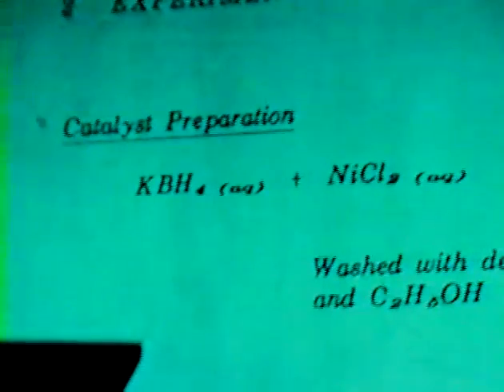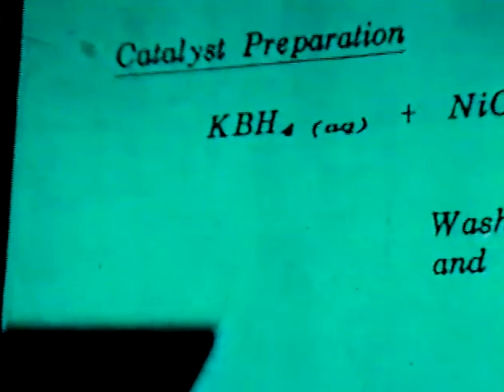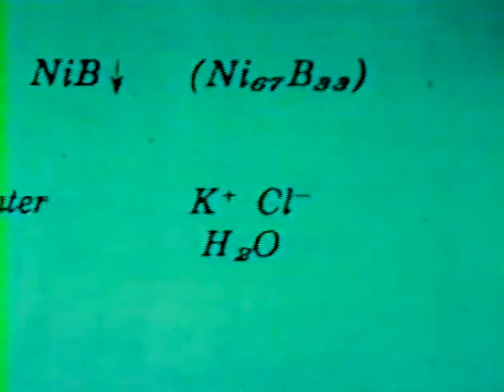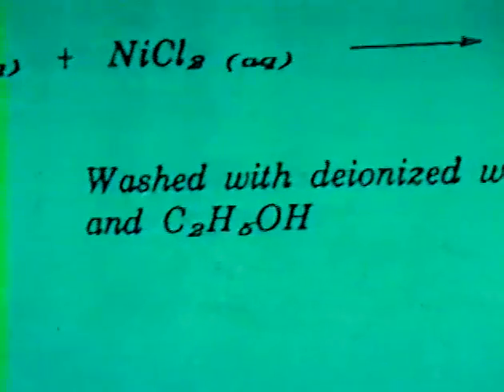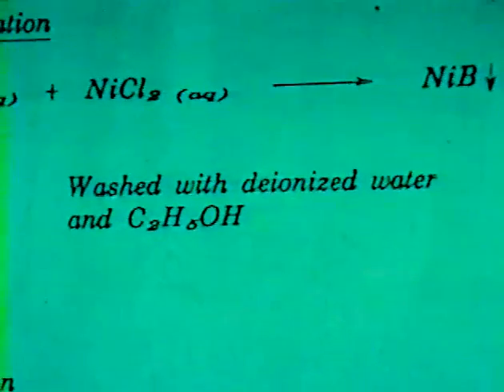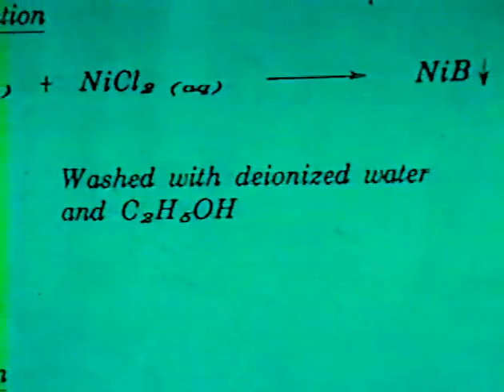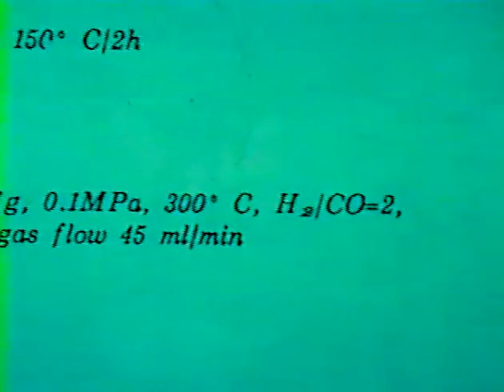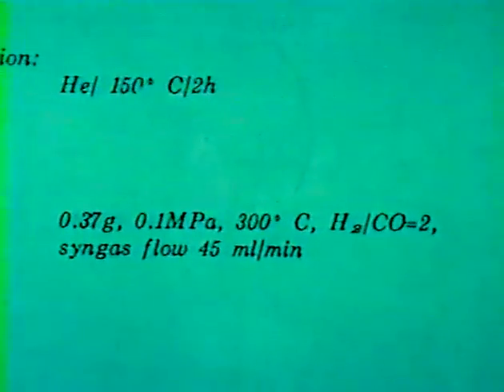We prepared the nickel boron catalyst by the reaction of nickel chloride and potassium borohydride in aqueous solution. We washed the samples in deionized water for the removal of potassium and chlorine ions. Then we washed the sample with absolute alcohol for removal of water. The samples were soaked in the alcohol for protection of the catalyst from surface oxidation by air.